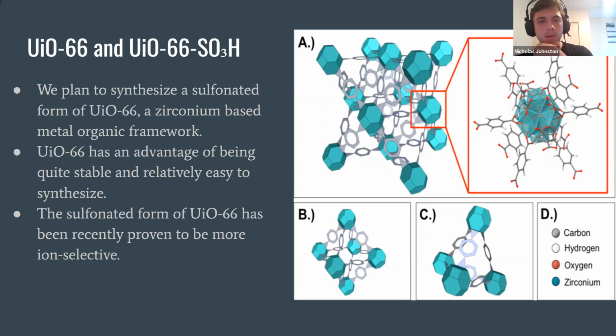The reason why we want to do that is this sulfonated UiO-66 was found to adsorb dyes, particularly methylene blue, much better than UiO-66. And I believe I mentioned that it's ion selective. What I mean by that is that it essentially completely absorbed positively charged dyes and rejected the negatively charged ones. I think the original paper was published very, very recently. They went through a whole bunch of these different dyes. Next slide, please.